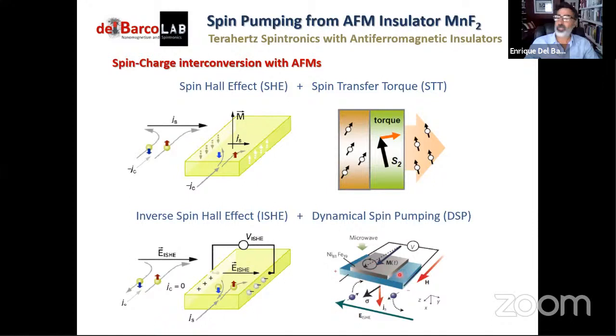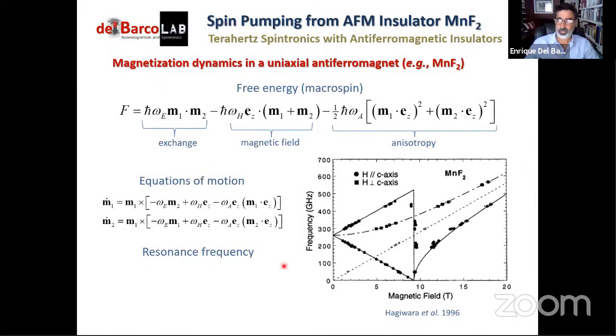So if we join these two effects in a device, and we have a magnetic material, or in this case an antiferromagnetic material, undergoing some magnetic dynamics, and a heavy metal adjacent to the antiferromagnet, the spin current that we generate dynamically by pumping spin angular momentum in every cycle of the oscillation will be converted into a charge current. And it gives us a very nice way to characterize the phenomenon.